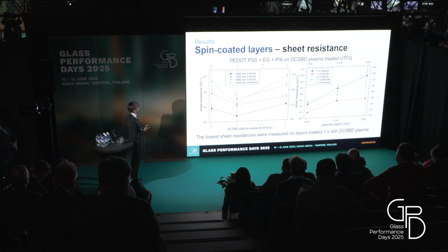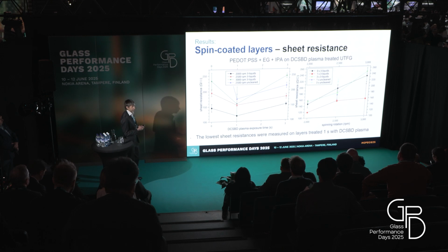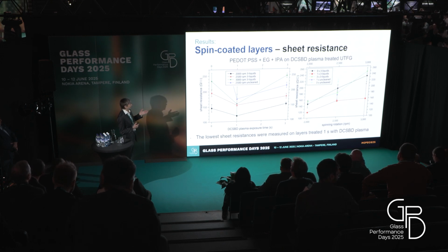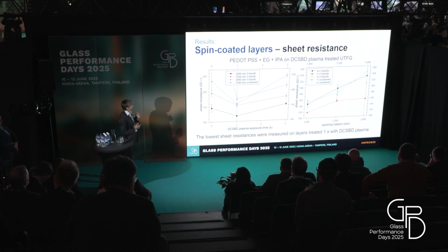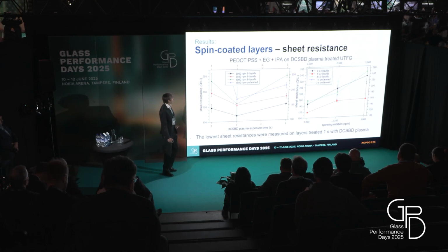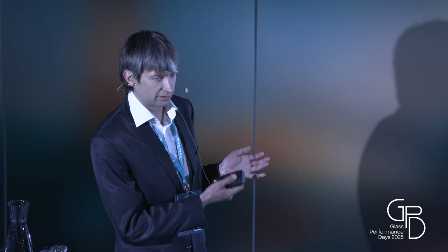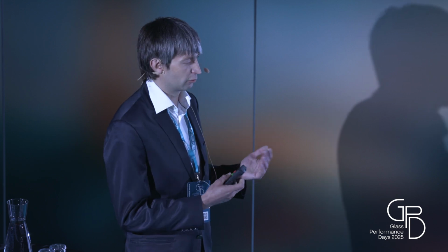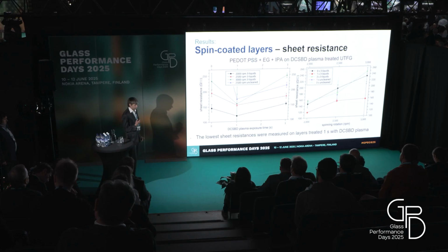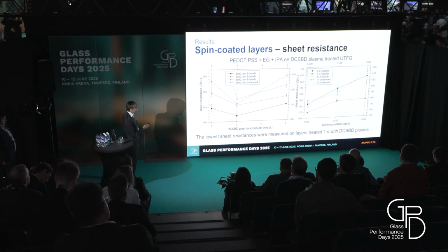And you can see that after 1 second, there was a very fast drop, and it was consistent for all conditions of rotations. We used plasma treatment with the solvent cleaning protocol, and also the plasma on a preliminarily uncleaned sample. And the effect was quite similar, even if we did not use the solvent cleaning protocol. So I can show you the next graph. And what this trend shows is that lowering the exposure time to plasma induced a better quality of coating, which is interesting, and it's due to the various processes in plasma, which cannot be on the same time scale.